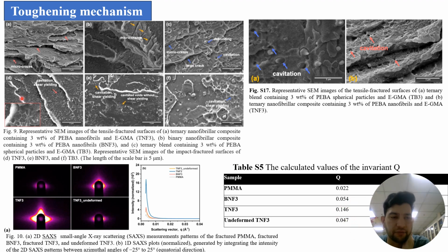Figure 9D to F. The impact strength of TNF3 was highest at 3%. The impact strength was very high when the concentration was 3%. Here is the D: TNF3 at 3%, the binary, BNF3, and the ternary, TB3, which contains spherical particles. So it decreases at higher concentration due to nanofibril agglomeration, so the strength decreases. The ternary blend did not show toughness improvement as their rubber concentration was too low. The fracture surface of the ternary blend shows large droplets.